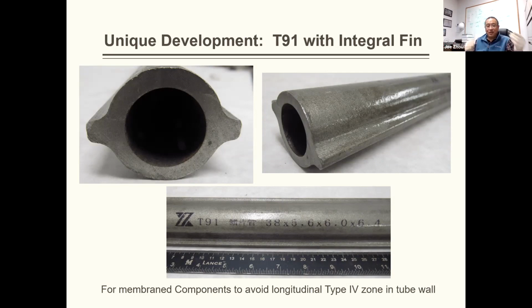If you use the traditional panel structure, you have to use a membrane bar with four longitudinal welds. For T91, as everybody knows, if you weld longitudinally on the tube surface, you create a Type 4 zone. The Type 4 zone weld strength reduction factor is 50%. That penalizes how you apply T91 tubing to construct the panel component. So what this unique tubing does is move the welds onto the pre-built fin. Previously, each tube had four longitudinal welds. Now you only need one pass or two passes. This not only solves the Type 4 zone issue on the tube wall, it also saves a lot of construction or manufacturing dollars.